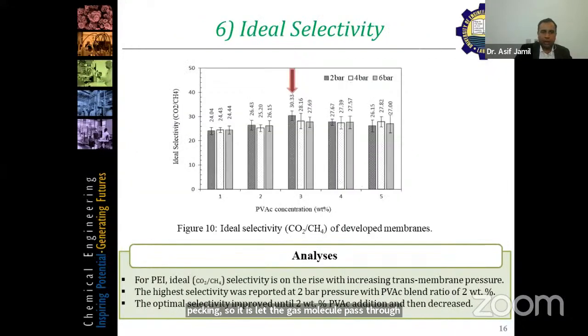And the other characteristic we want is the selectivity. We want CO2/CH4 selectivity to be higher, and that's why here, when we increase the concentration of polyvinyl acetate, the selectivity keeps on increasing up to a certain level. After 2 weight%, it goes down. The effect is negative because after 3-4 weight%, the concentration of polyvinyl acetate is higher, which is rubbery in nature. So that's why the performance goes down.